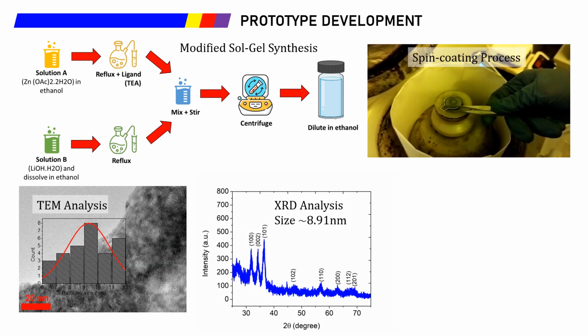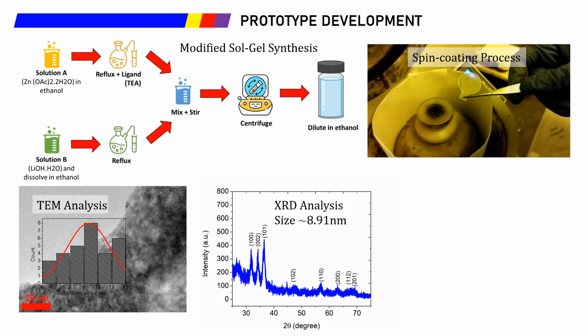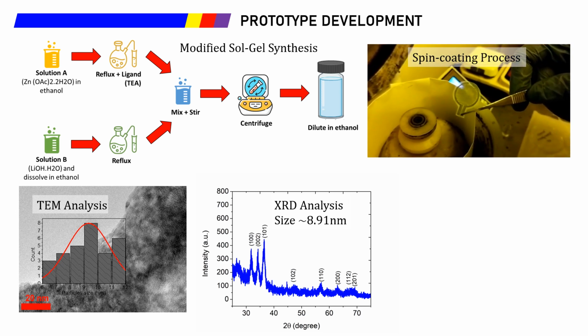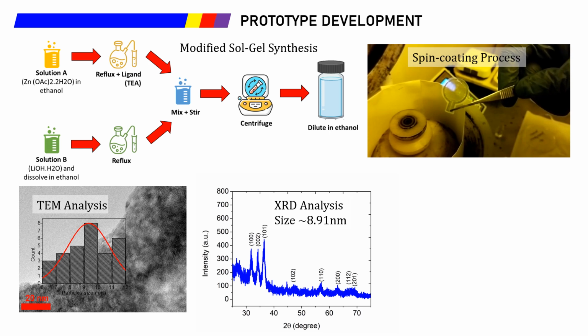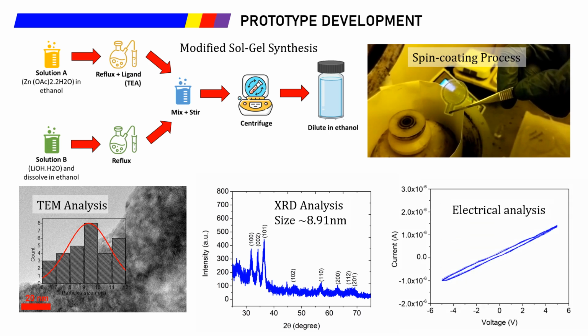The size of the synthesized zinc oxide quantum dots is less than 10 nanometers, proven by transmission electron microscopic analysis and X-ray diffraction. The sensor shows stable and reliable electrical properties under a 100 times reading cycle between -5 to 5 volts.